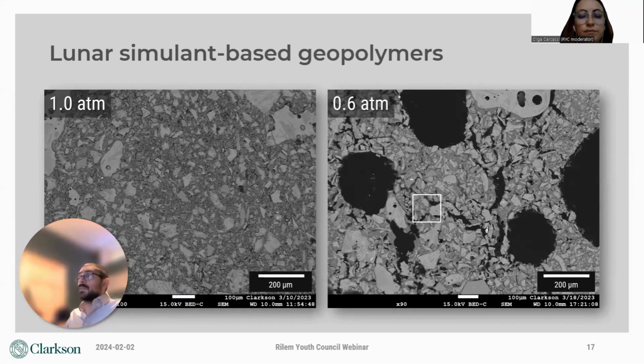Reduced gravity is not the only challenge posed by the lunar environment. We also see dramatic temperature fluctuations and the lack of an atmosphere. On Earth, atmospheric pressure helps with the closing of air voids in the fresh concrete. The image on the left is lunar concrete formed at 1 atmosphere of pressure, and the microstructure is dense and well consolidated, and there are no macroscopic air voids to speak of.